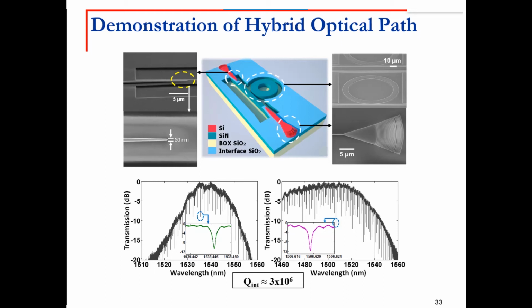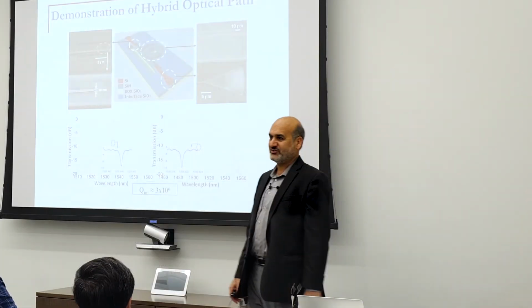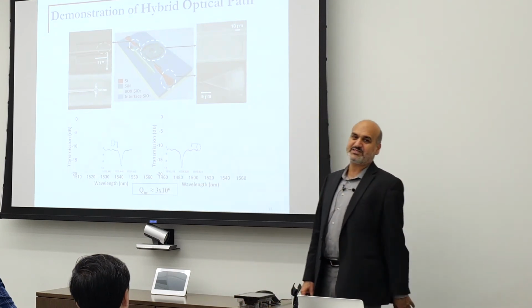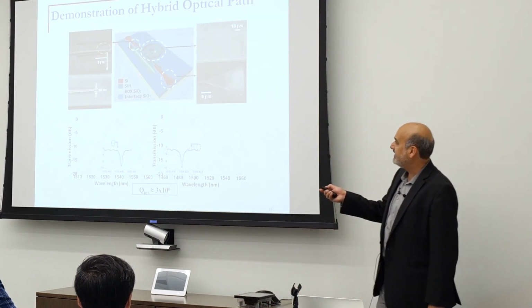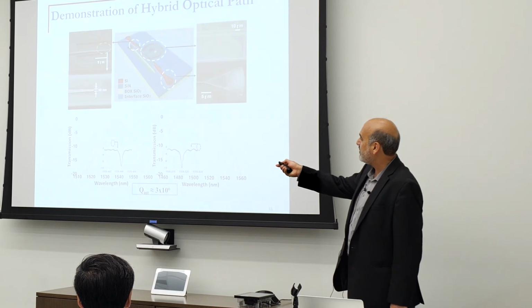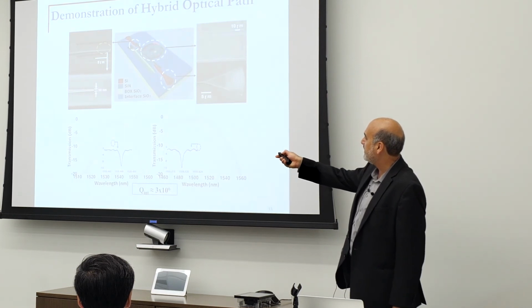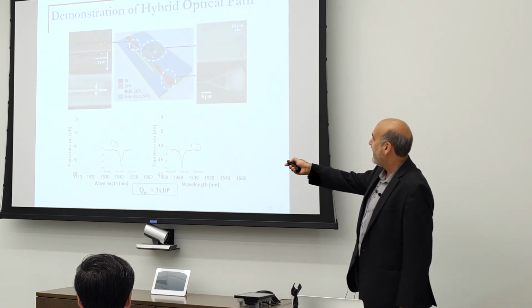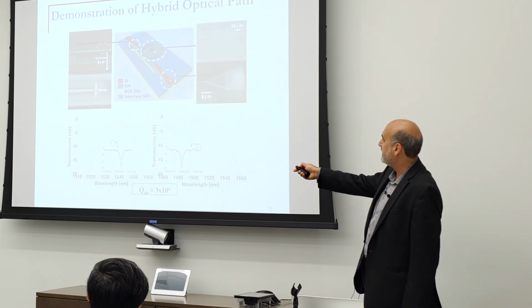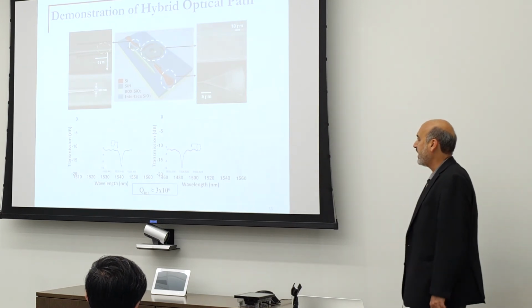Now, to show the potential of this technology, we go from the top using a grating that is shown over here. Light goes into silicon. We taper silicon down to 50 nanometers. That automatically pushes the signal into a nitride waveguide underneath with better than 97% efficiency. And then the signal goes into nitride, couples into the resonator in the nitride, and then it comes back to silicon, comes back to the grating, and comes back up.